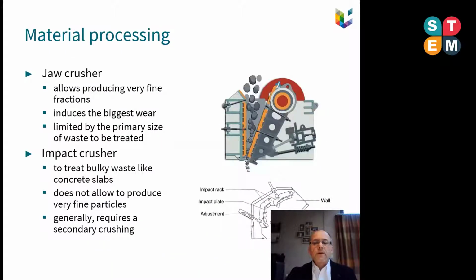This crushing may be obtained by mainly two types of crusher. A jaw crusher allows to produce very fine fractions and can, however, induce a big wear process. That means that we will have to replace continuously the jaws in the system. The second type of crusher is the impact crusher that can be used to treat bulky waste like concrete slabs, etc., but doesn't allow to produce very fine particles and generally requires a secondary crushing.